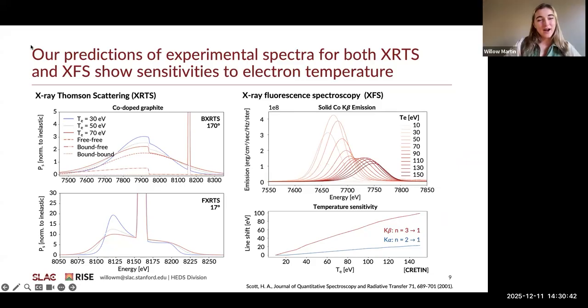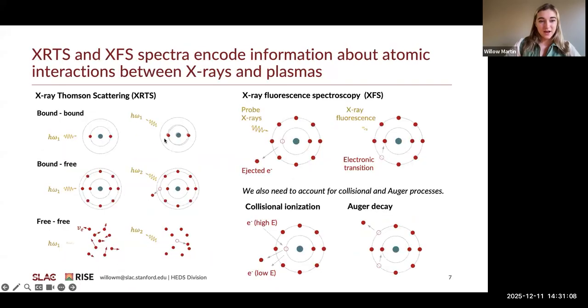Yeah, of course. So I think the easiest one to get a handle on would be non-collective X-ray Thomson scattering. If you look at the upper left-hand side here, the primary constraint on electron temperature is coming from the inelastic feature, in particular the free-free feature. Let me go back a slide. There are three primary contributions to X-ray Thomson scatter spectra that you can decompose. That decomposition is something called the Chihara decomposition, where you calculate the contribution to scattering from three different kinds of interactions.